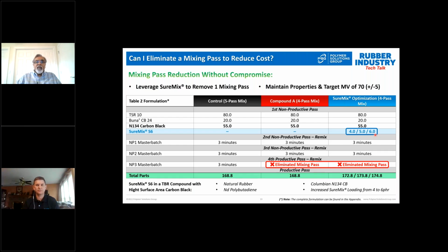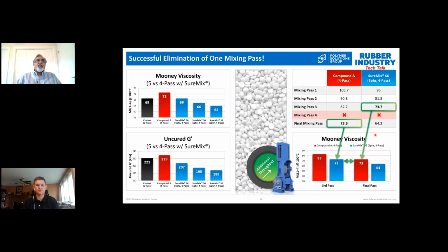So as you can see over here, everybody looks at Mooney, which is fine. You can see an increase in Mooney as one pass is taken out, as you go from 5 to 4 pass. And when SureMix is added, you can see again a drop in Mooney. These are all 4-pass mixes.